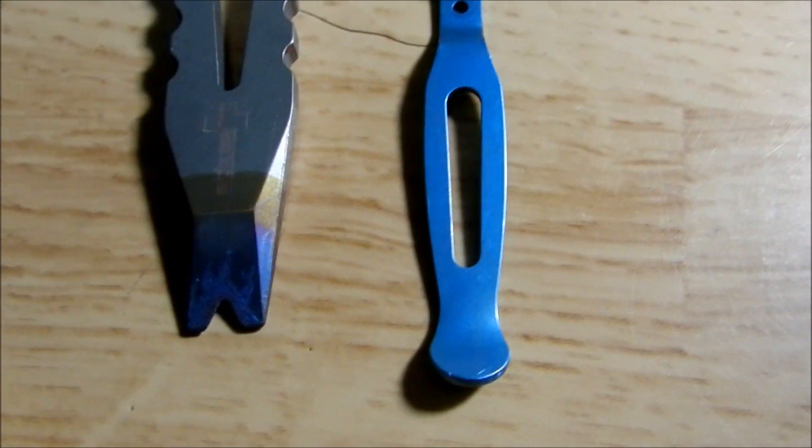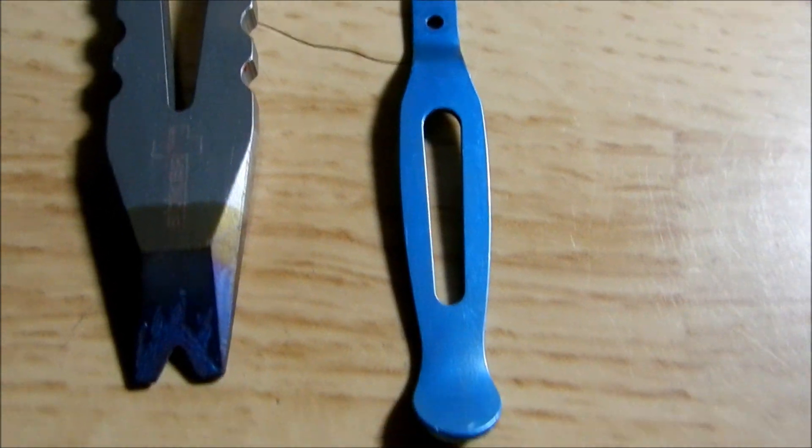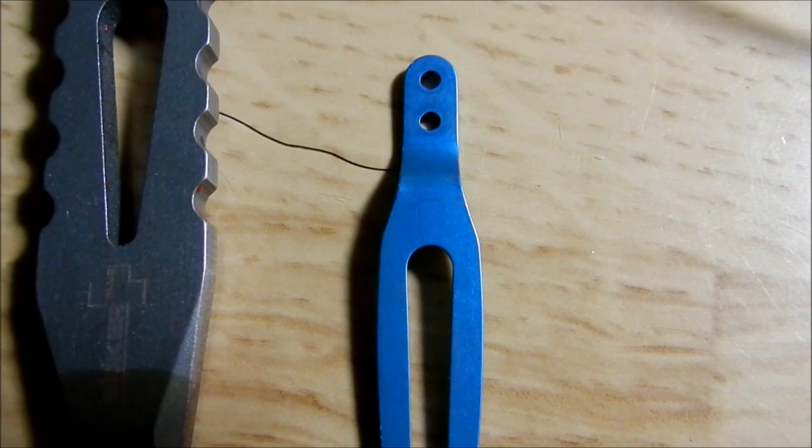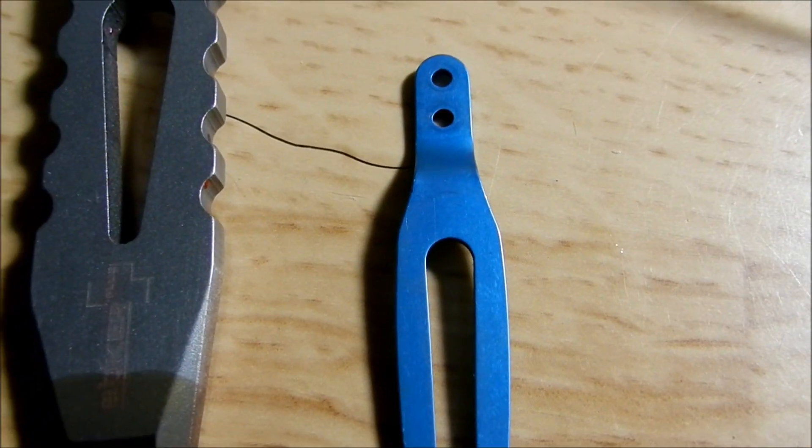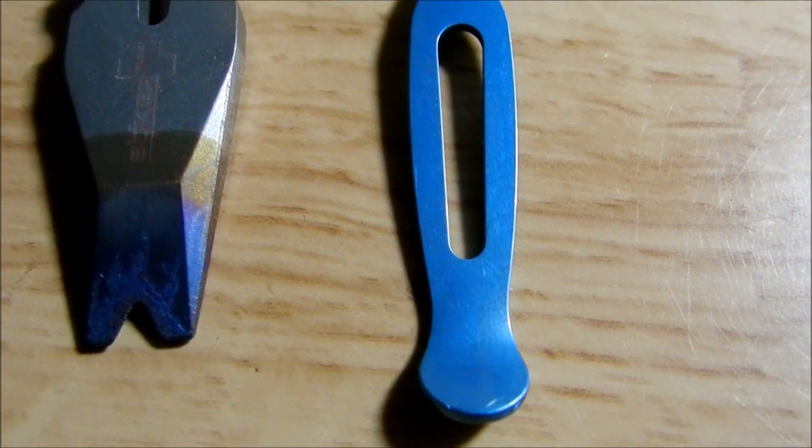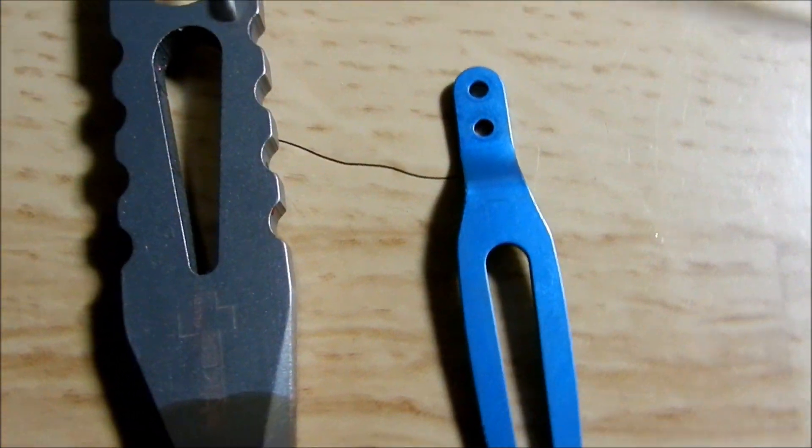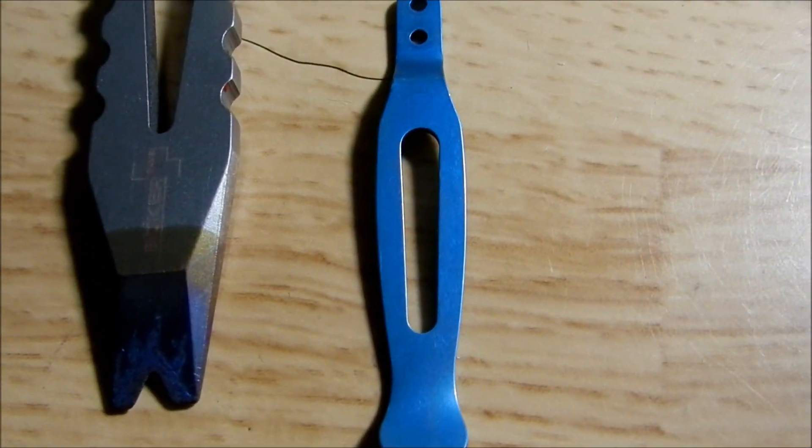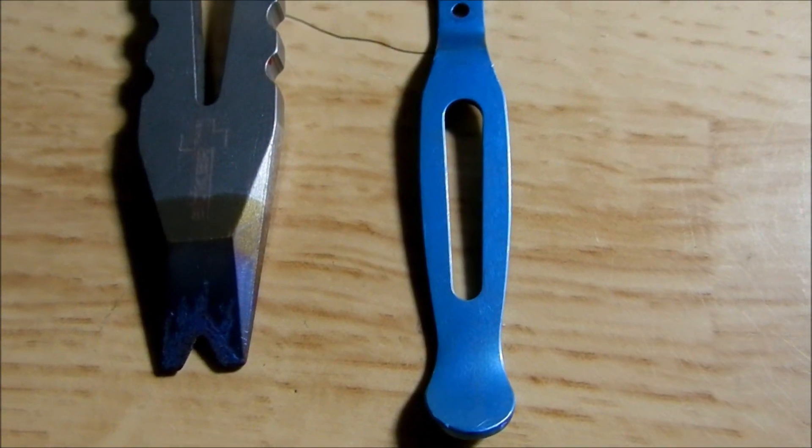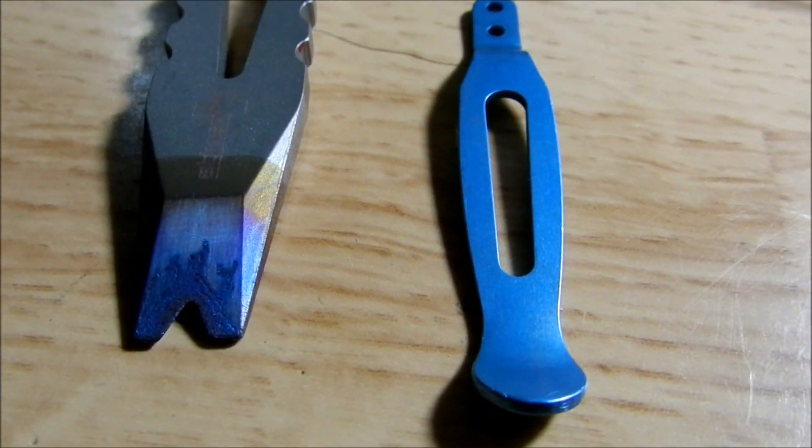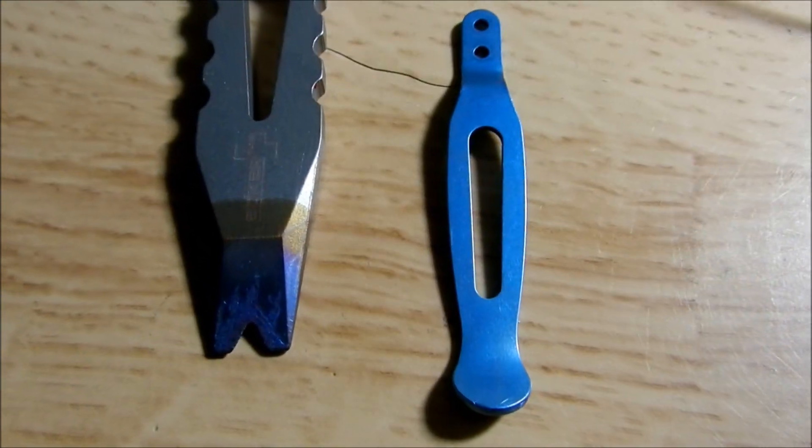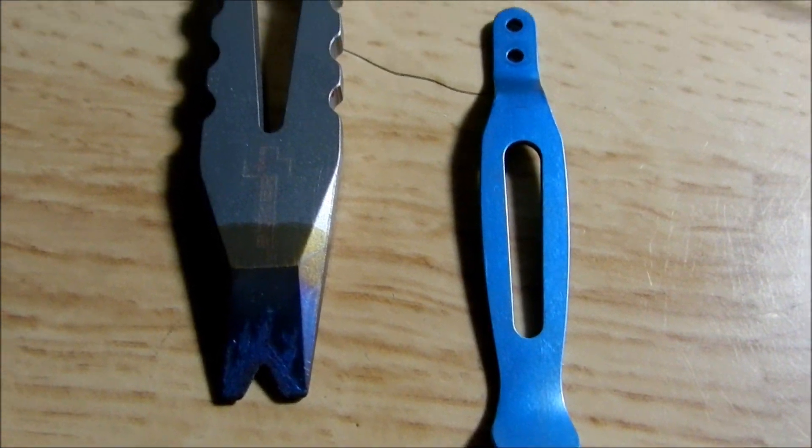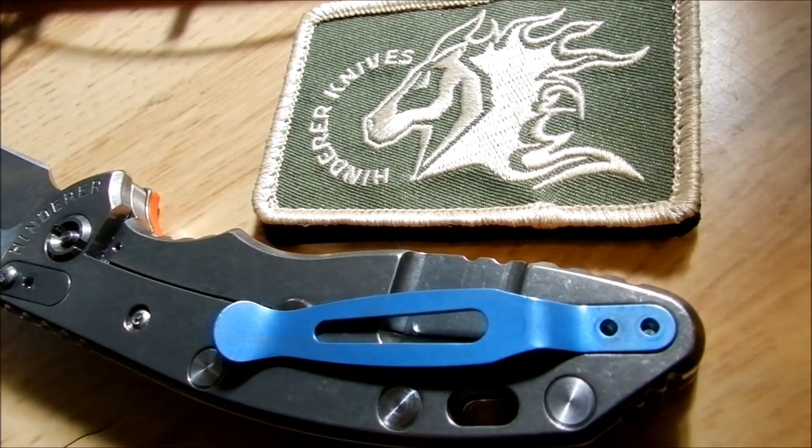Twenty-five volts. All right I'm done with the pocket clip that is at exactly 28.0 volts. This is blue. I was trying to get a darker blue but I went past it. A darker blue would be at 26 volts and once you get to 28 it turns blue and then once you get to around 30 it'll be a light blue. So I'll try this out. If I need to change the color all I have to do is use the multi-etch and it will remove the anodizing. I can redo it.